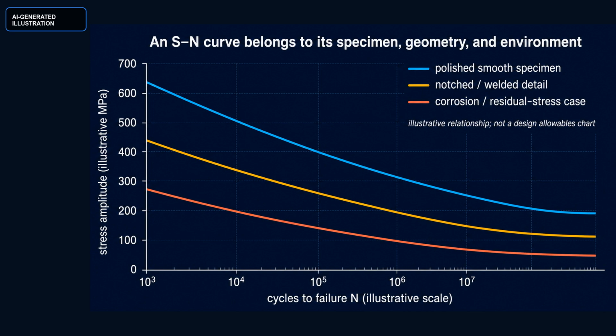The other familiar fatigue tool is the S/N curve, stress amplitude against cycles to failure. It is useful, but it belongs to a specimen, finish, geometry, and loading protocol. A polished smooth coupon can last much longer than a welded or notched component at the same nominal stress. Surface roughness, residual tension, inclusions, corrosion, and a crack that is shorter than the test standard can all move the curve. Even an apparent endurance limit is conditional. A component designer must ask which flaw population and load spectrum the curve actually represents.